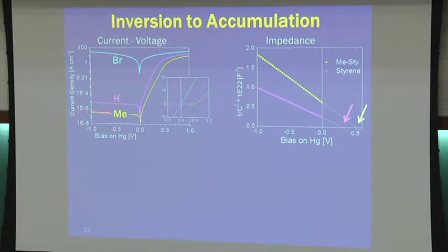And you see that we have 8 orders of magnitude just by changing the substituent. So it's a huge effect, and the barrier is in the silicon. It's not a direct molecular barrier, but an induced barrier, and it's a very strong expression of chemistry. So we are very sensitive to minute chemical changes.